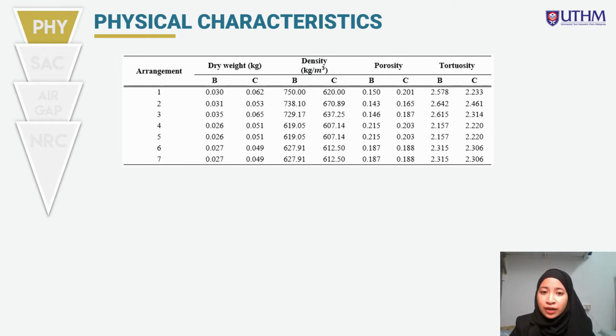The table shows the physical characteristics of these samples. Since we are using 2 different stalk diameters, sample B is with a bigger stalk diameter of range 4 to 7 mm, and sample C is with a smaller stalk diameter with range of 2 to 4 mm. Arrangements 1, 2, 3 are fibers in axial configuration, where arrangement 1 means a layer of axial configuration, arrangement 2 means 2 layers of axial configuration, and arrangement 3 is fiber arranged in 3 layers of axial configuration. 4 and 5 indicate horizontal and cross configuration respectively. Lastly, arrangement 6 is the combination of horizontal and axial configuration, and arrangement 7 is the combination of cross and axial configuration.